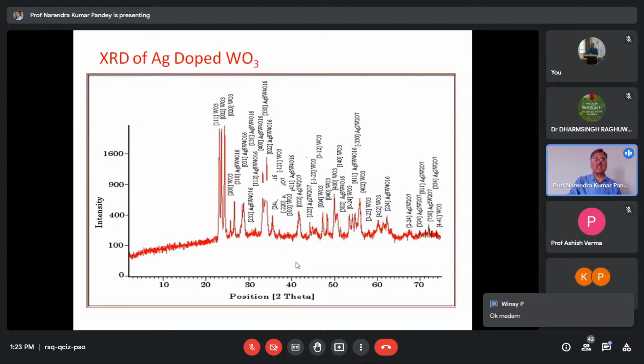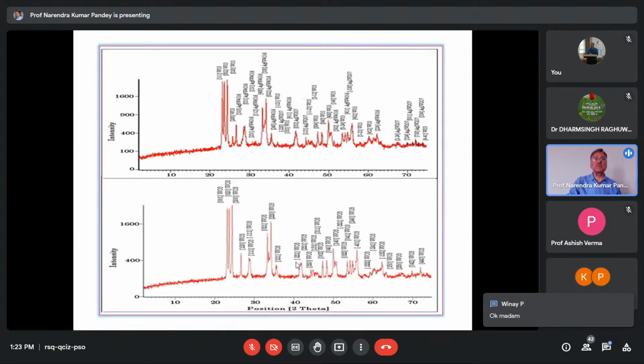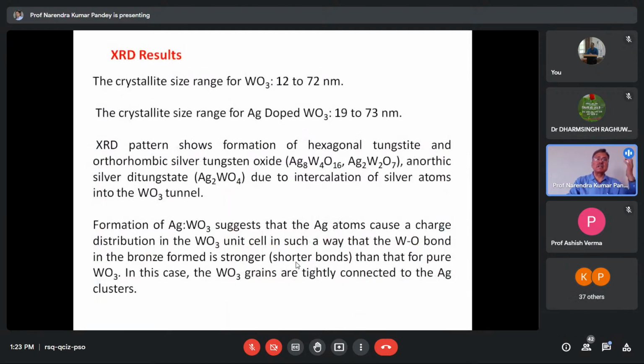These are the XRDs to understand what exactly the phenomenon has gone through. This is for WO3 and this is for Ag doped WO3. XRD result: for WO3, you are getting a crystallite size of 12 to 72 nanometers. Like I said in the beginning, when we are talking about nanotechnology, the size should be between 0 to 100 nanometers. The crystallite size for Ag doped WO3 is 19 to 73, so the range is in the nanometer range.